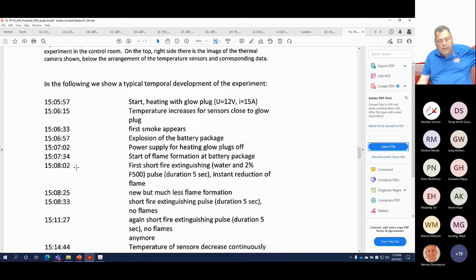So from 8:02 to 8:07, we get an instant reduction of the flame and a big reduction of the heat. And then we're waiting. See, we don't do the second burst for another 30 seconds. So what we start to see here between 8:07, because this was a 5-second burst, and 8:25, so we got about 20 seconds, we get a little more flame, but much less flame formation.